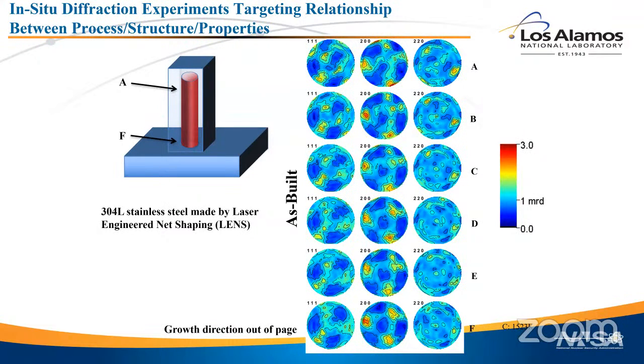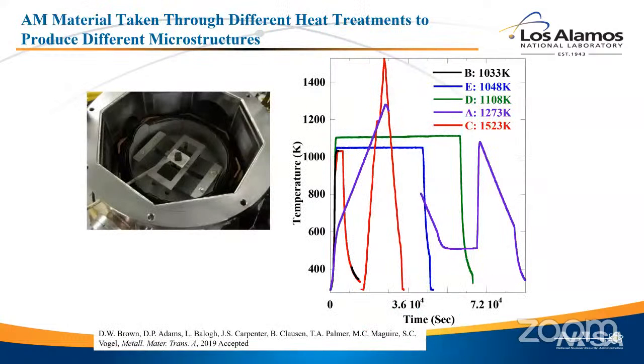Now this isn't a perfect experiment, because we all know that AM, as a function of height, you can get different properties. That's because at the bottom, it cools faster than at the top. And you can see that in the texture here a little bit. There's a stronger texture down here in F than there is higher up, due to the higher solidification rate. But we're going to treat these 6 samples as if they're all the same. That's not a perfect assumption.